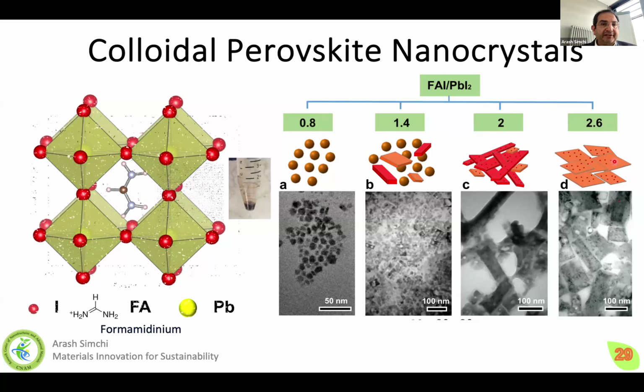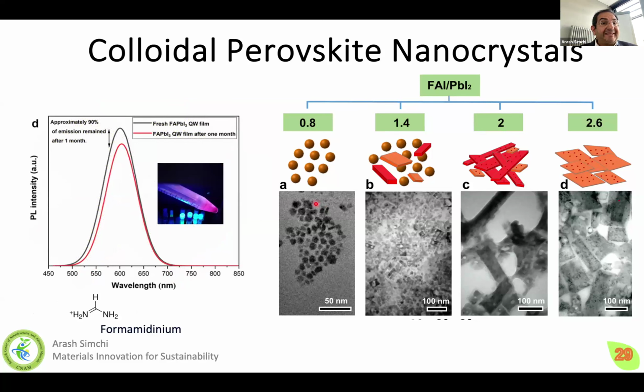And the good point about this technology is that the stability of perovskite colloidal nanocrystals increases significantly. As you know, colloidal perovskites are very interesting at the moment for industrial application, but the main challenge is how to make them stable. Because, for example, the PL intensity decreases in just a few days. But we show that even in a humid atmosphere, 60%, 40%, we can keep the PL intensity for a month. And it's a great job.